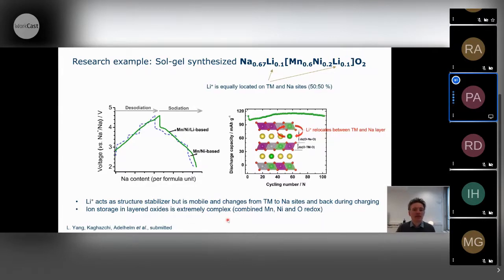This is a more recent example that we studied. So this is a sodium manganese nickel oxide, and again we add lithium as a stabilizer, but now half of the lithium sits in the alkali layer, together with the sodium, and the other half sits in the transition metal layer. The lithium does not actually go out of the material during charging, so it really remains in the structure. But what happens during charging is that the lithium changes its location, so the distribution of lithium ions in the structure changes during charging. And when you charge this material, first lithium goes into the alkali layer to occupy empty spots, and if you do further charging, the lithium moves backwards again. So quite an interesting behavior, full of dynamics, so to say, and not very well understood.